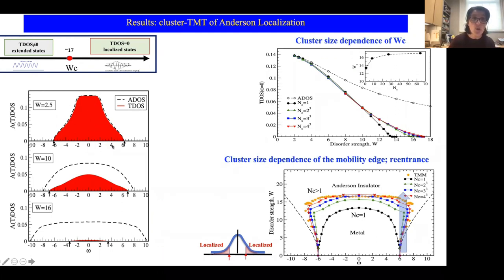This is for weak disorder, when average and typical are about the same as expected, because in this regime you still have self-averaging satisfied and most probable and average values are about the same. However, as you increase the disorder strength, you see that the typical density of states starts to get suppressed and it starts to become zero starting from the edges, as expected, because localization is happening first at the edges. And then as you increase disorder strength further, the typical density of states gets suppressed, okay?